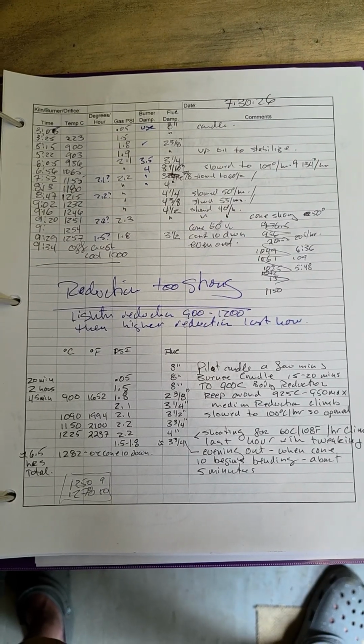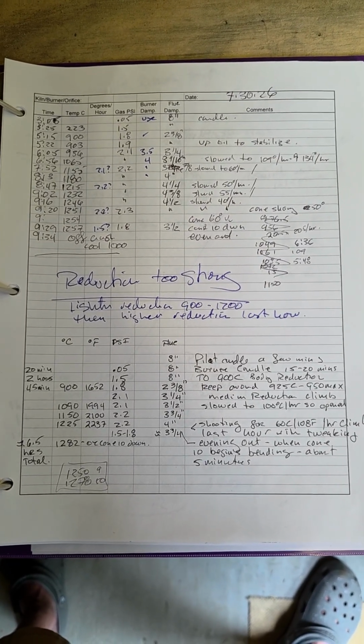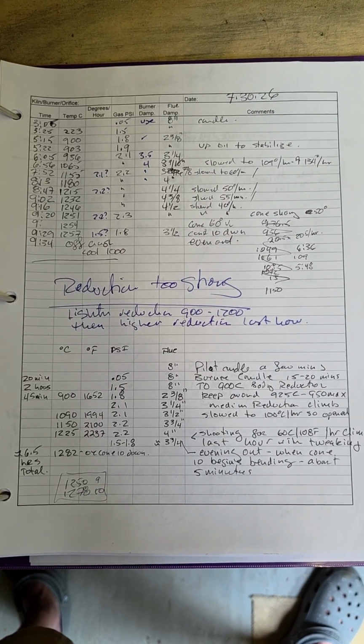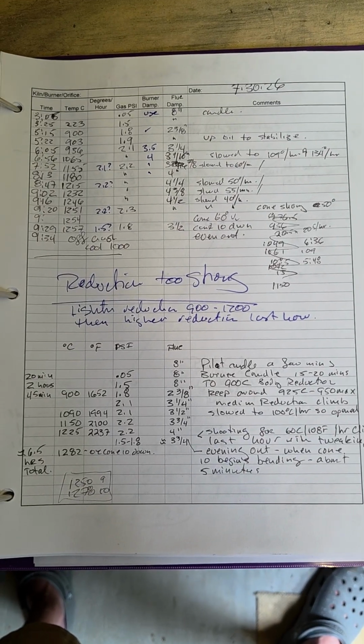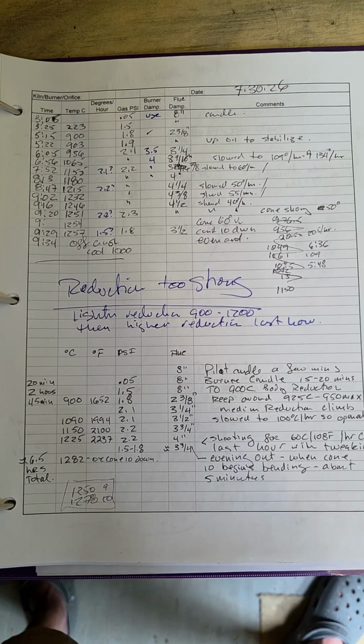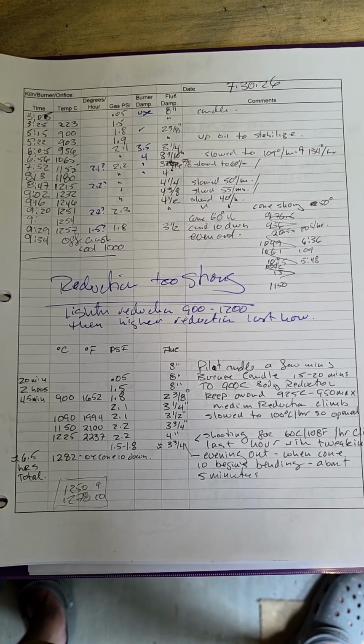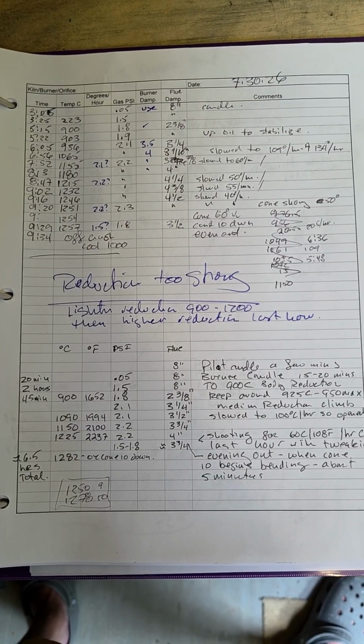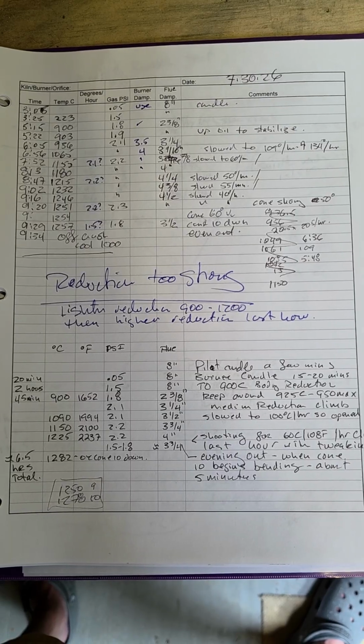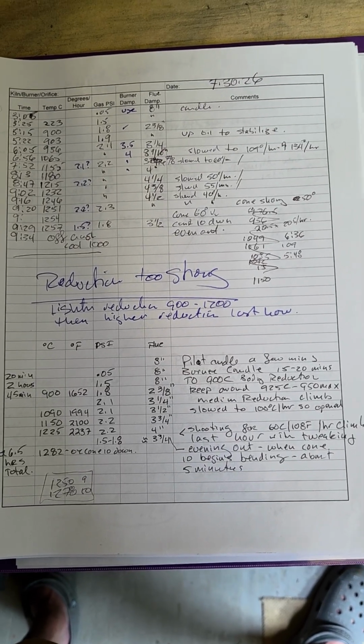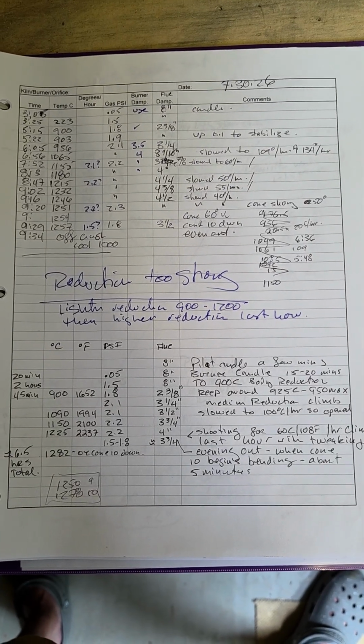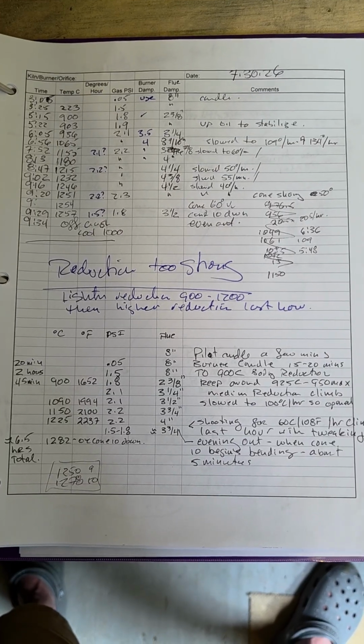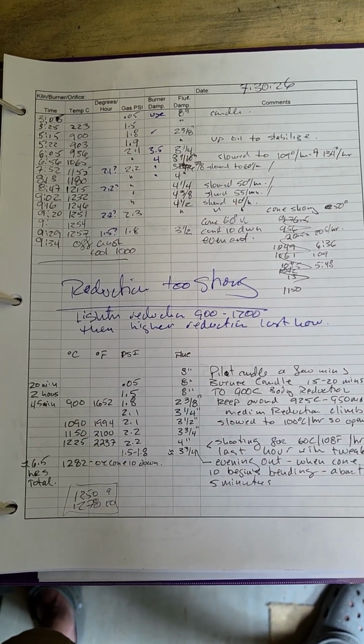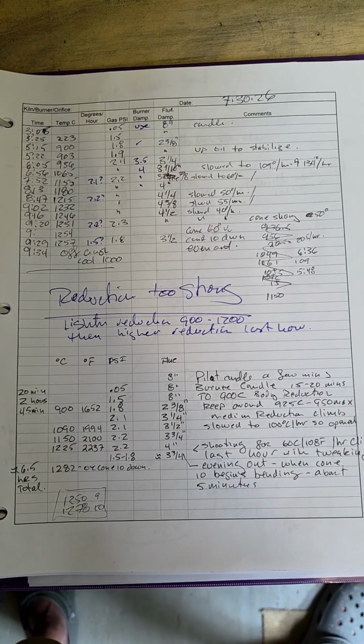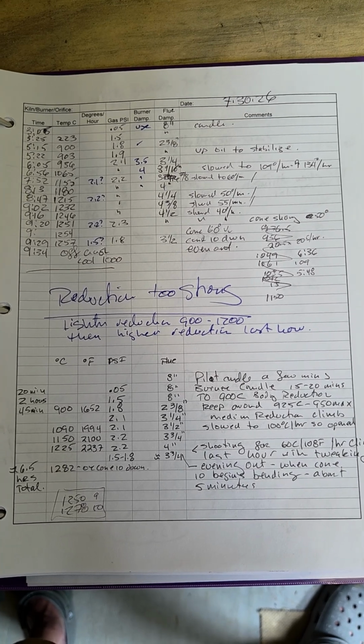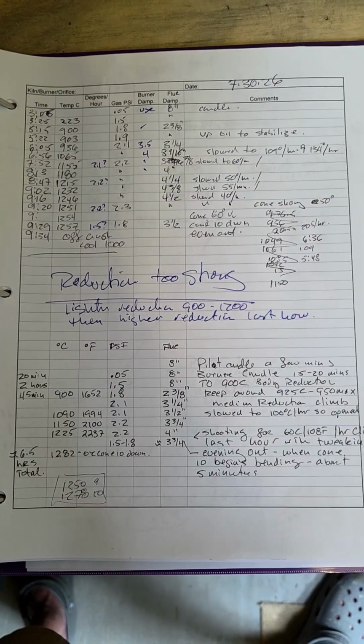And I've got to note the reduction was too strong. I hadn't fired in a while, and for whatever reason, the numbers that I used provided just a little stronger reduction than I needed, and I could actually see it after it came up to 900 degrees, where I start body reduction and stay there for about 45 minutes. There's usually not much of any reduction flame visible until it gets up around 1150, 1200 degrees. I had a reduction flame right away, which should have showed me that my climbing reduction was a little too strong. So this takes about 2 hours to get to 900 degrees centigrade, and at that point I stall the kiln out and I do a 45-minute body reduction.